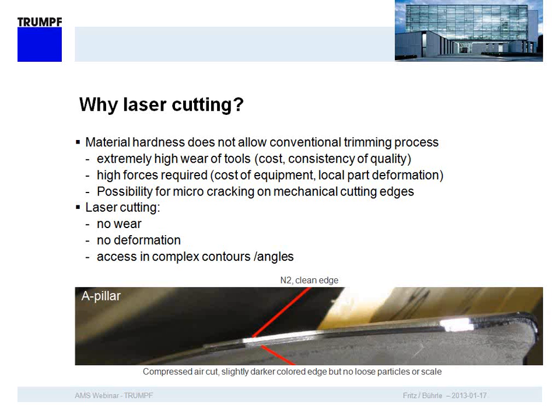The two typical laser processes that are used for these materials are nitrogen as a cutting gas, but as a newer trend, or since a few years, I think most of our customers also switched over to compressed air cutting, just because of the savings in processing cost. The cut speed and the cut quality is pretty much the same. The difference is that you have a shiny edge with nitrogen and you have a little bit of discoloration with air.